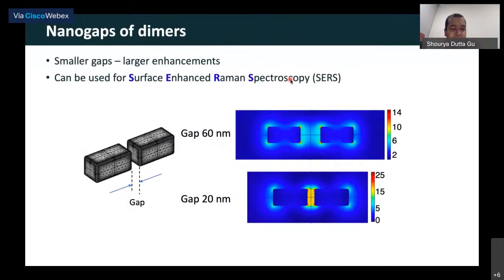So now, let us take this case of a plasmonic dimer. So we have two gold cuboids. So both of them are made up of gold. This size is around 60 to 80 nanometers, and the gap we can vary.